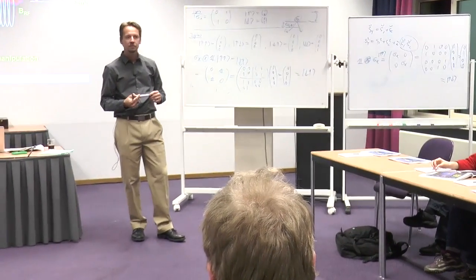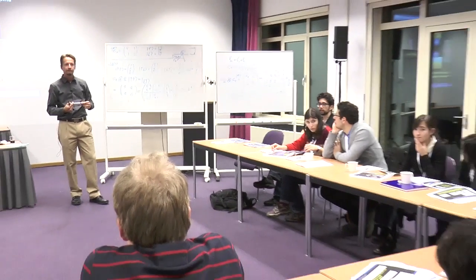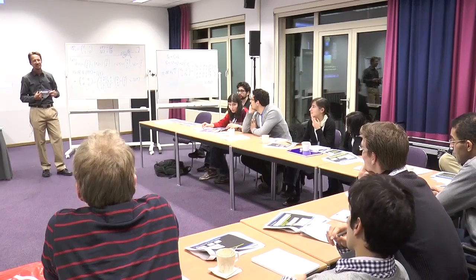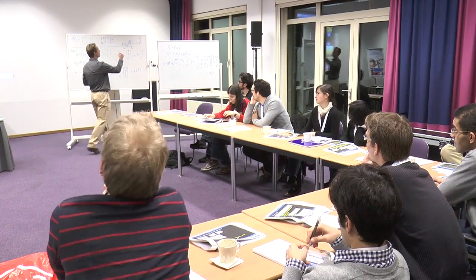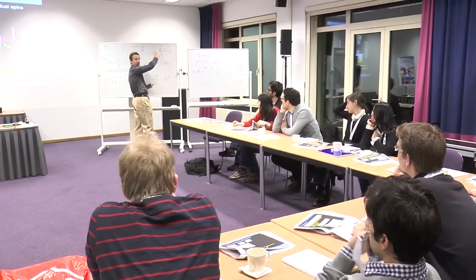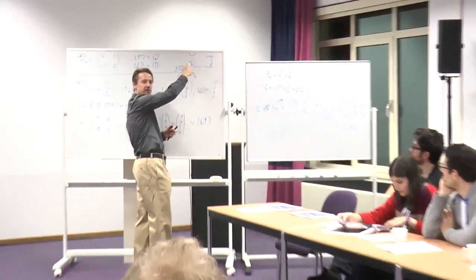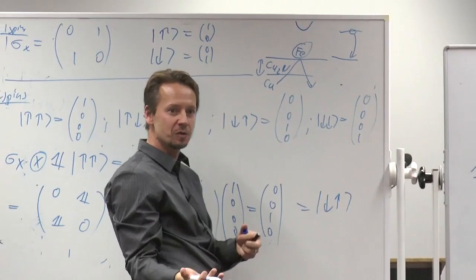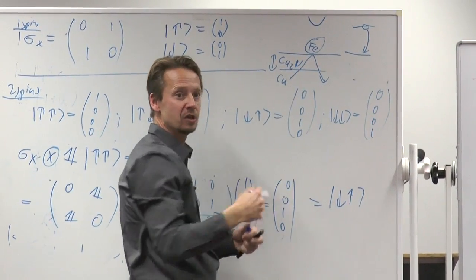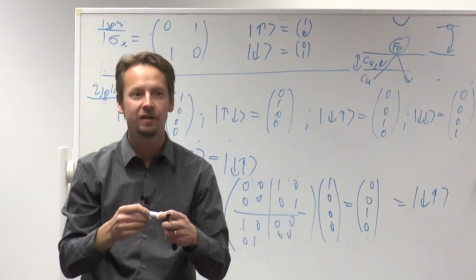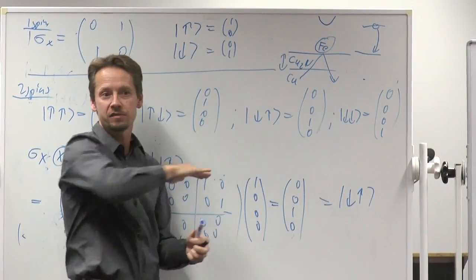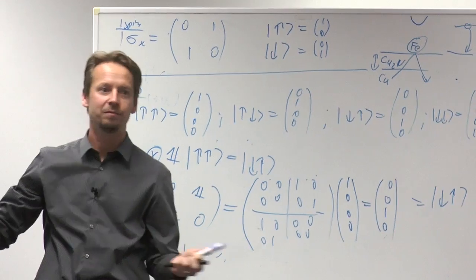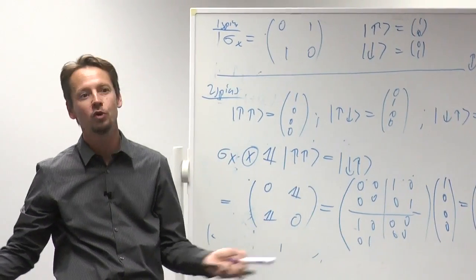What's the biggest downside of increasing this insulator? Things become more difficult. Yeah, that's right. So you need to find a balance. Of course, we want to be able to tunnel through this. So we need to find a balance where we can still get enough current through this to do our measurement, but where this process here becomes long enough that it doesn't really matter. And so what we're doing is, on copper nitride, we can't make this any thicker. It's just self-limiting to one layer. Pain in the neck, but that's the way nature works in this case.